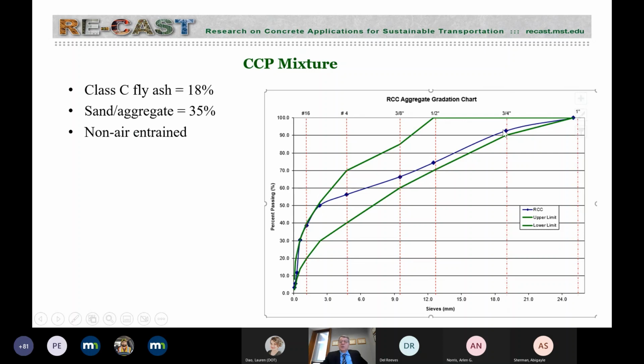So the aggregate size distribution that was used and the combined aggregate size distribution. The sand to aggregate turned out to be by volume 35%, the fly ash versus the binder 18%, and the mixture was not air entrained. It's impossible to air entrain something like this.